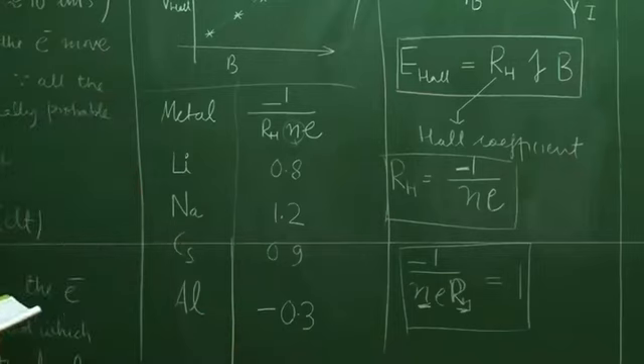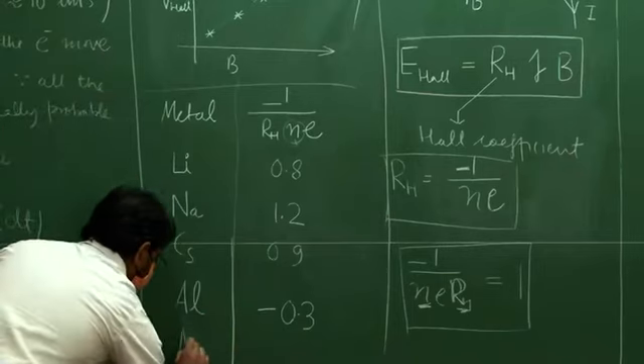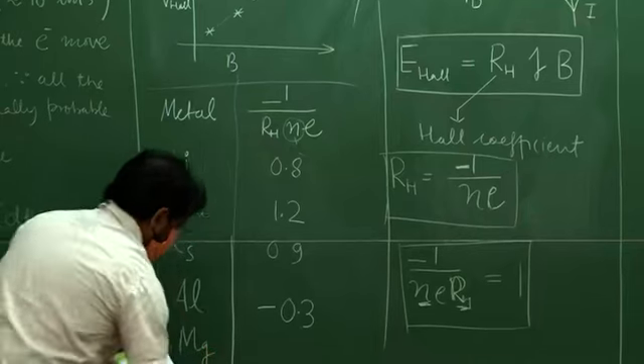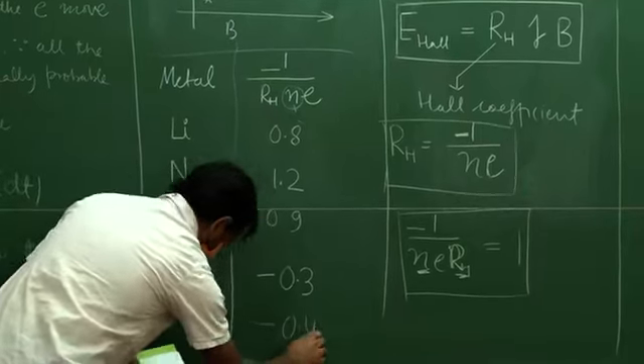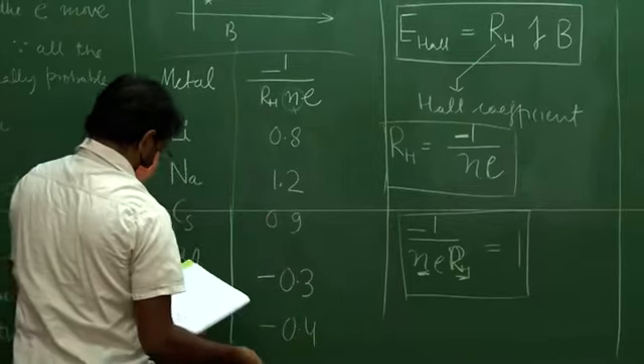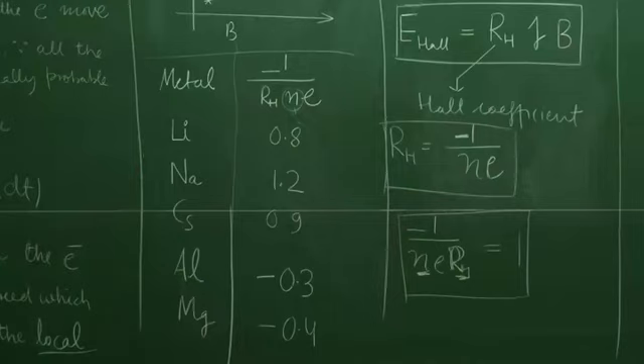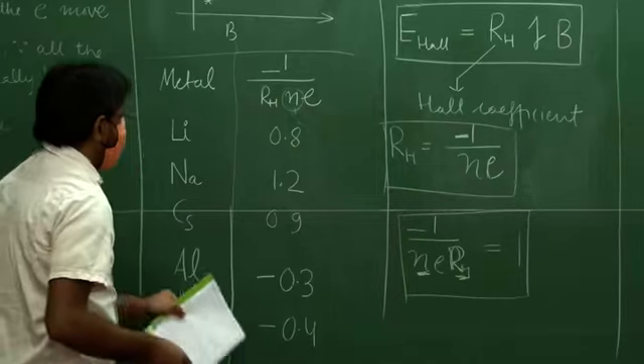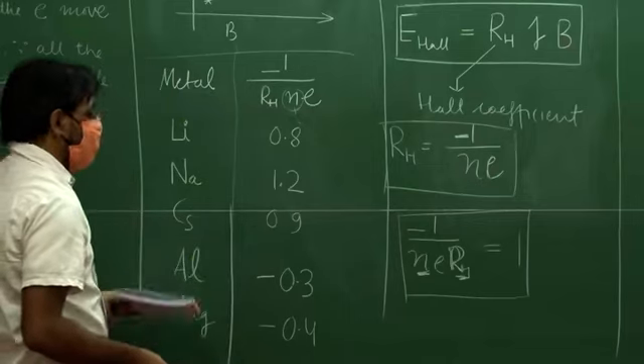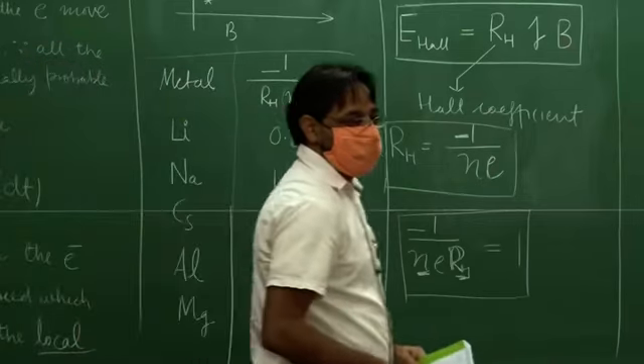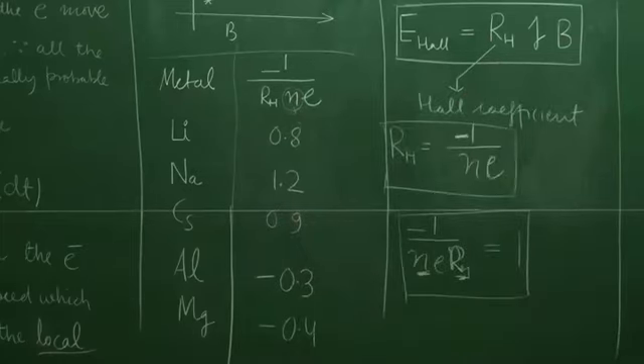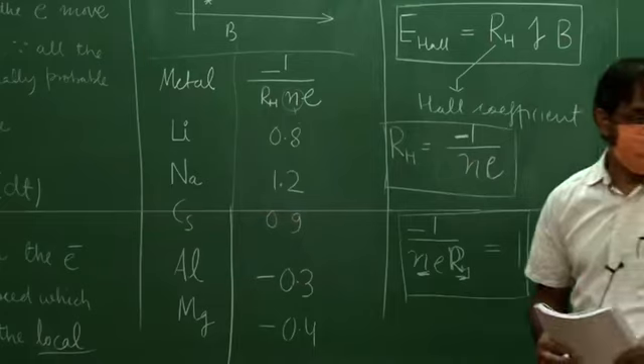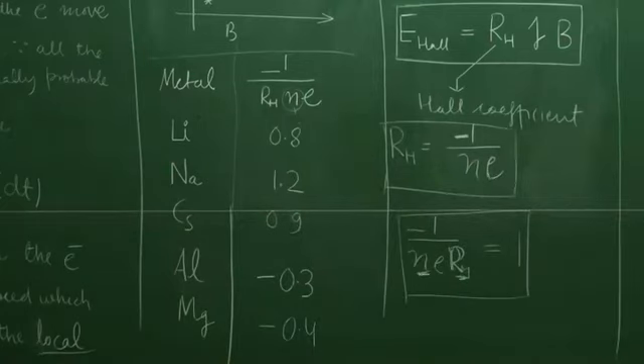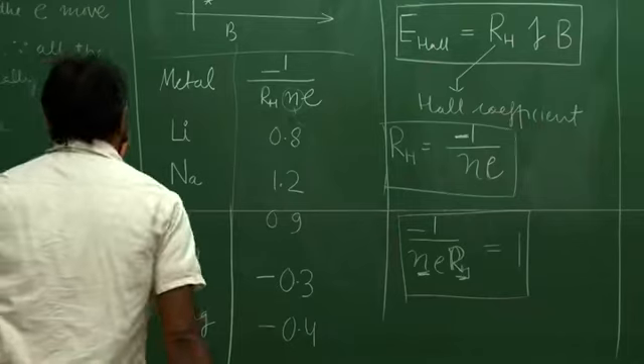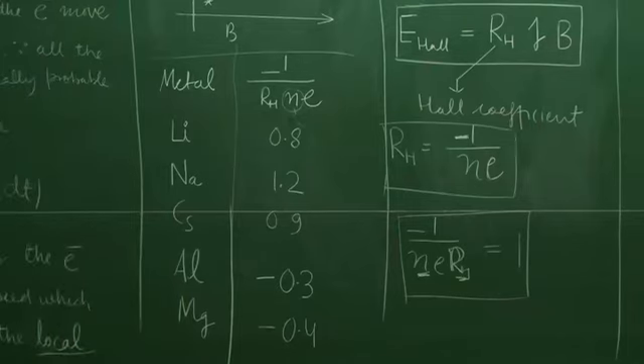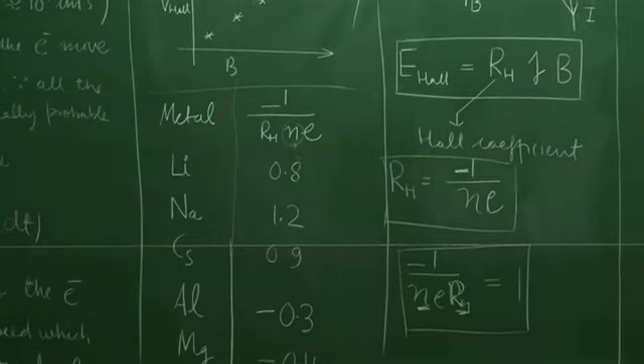And aluminum is not the only exception actually. You have magnesium, which gives 2 electrons, it is minus 0.4, which is once again negative. And you have then indium, which is also negative, and there are many others for which this quantity is negative, or in other words, the Hall coefficient is positive, or in other words, the carriers are positive. So how should we understand that? We cannot understand that within the framework of Drude's theory, right? So that's another problem. So this is about the Hall effect vis-a-vis the theory of Drude.